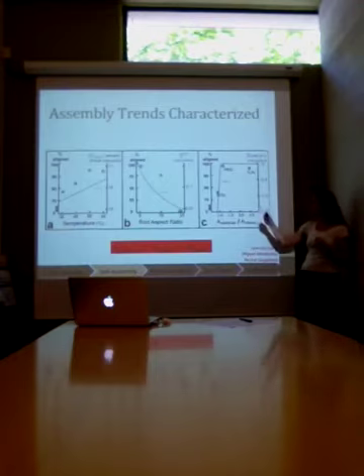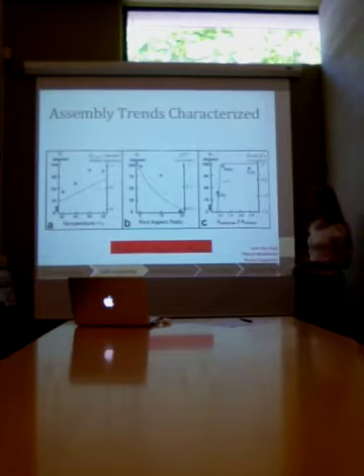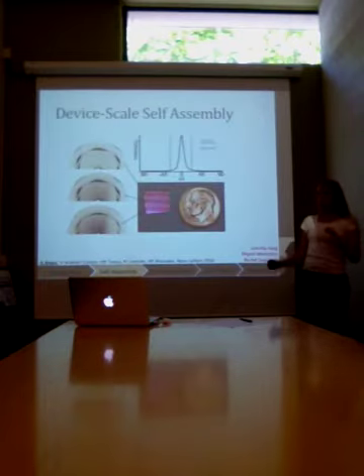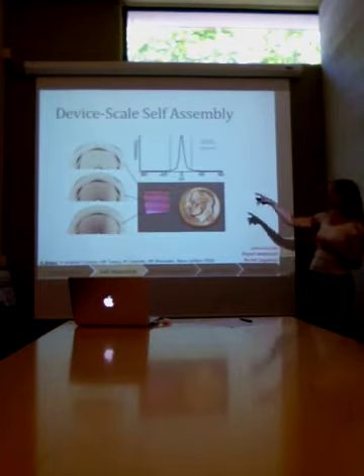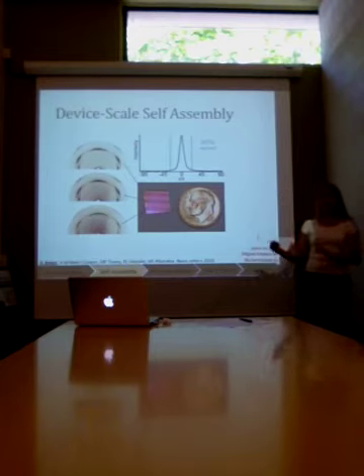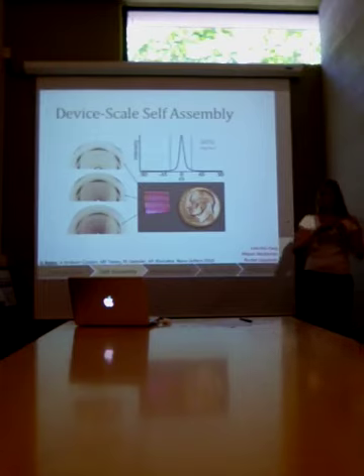these very large rods. Finally, we plotted the degree of alignment as a function of the substrate Hamaker constant, or van der Waals coefficient, and we were able to develop a heuristic for the best alignment. This heuristic was that we wanted the Hamaker constants of the system components to fall in decreasing order, starting with the substrate and the solvent and then the ligands. Using all of this, we were able to align 96% of the nanorods on 1 square centimeter. So we've now accomplished this goal of getting something that's starting to look like device size, that's a thin film, single crystal semiconductor.